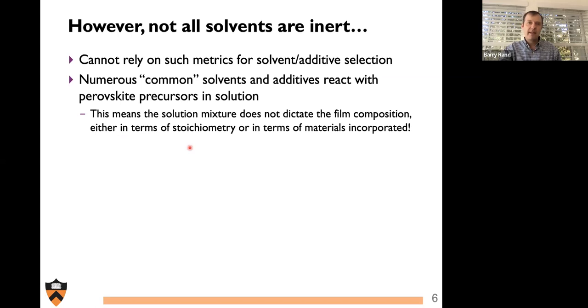That means that the solution mixture does not necessarily dictate the film composition, either in terms of stoichiometry or even the materials that are incorporated, because a reaction could lead to byproducts, which may very well be replacing your expected reactant in the final perovskite film.